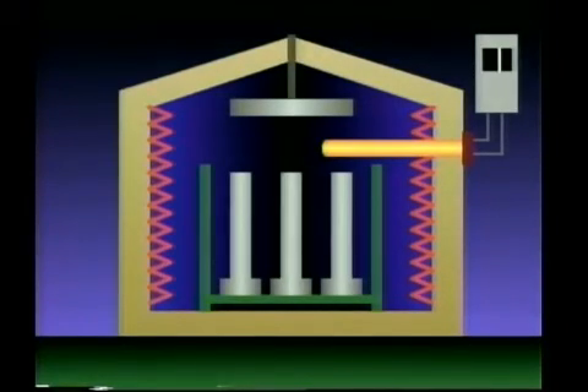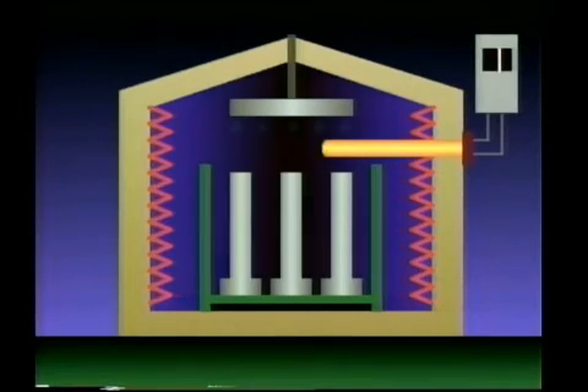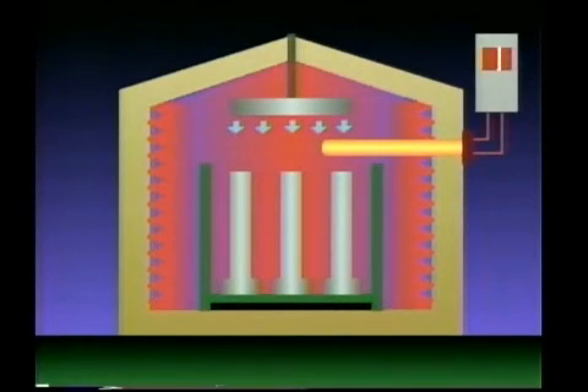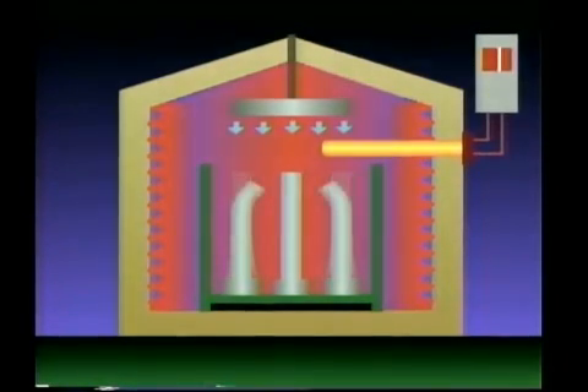Experience has shown, however, that aluminum heat treating furnaces, particularly in the range of 800 to 1000 degrees, can sometimes, if designed improperly, cause a problem whereby the radiation from the sidewalls of the furnace can cause overheating. This condition has been known to cause serious problems of overheating and eutectic melting in structural components. Often this condition is not detected through inspection procedures. Thus, the heat treater must have complete assurance that the solution heat treating furnace has no radiation heating problems.